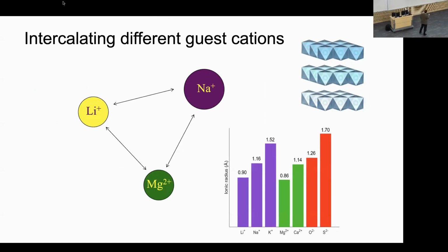So one thing we can do is take this layered host material and systematically compare what happens if, instead of putting lithium between these layers, we put sodium, which is bigger. This is the ionic radius of lithium, and that of sodium is bigger. So we can independently look at the effect of size on how these intercalation compounds behave. Or instead of lithium, we could put magnesium, which is 2+ but has roughly the same ionic radius. So along this axis, we can explore the effect of oxidation state without changing the size. So we can independently look at different effects.